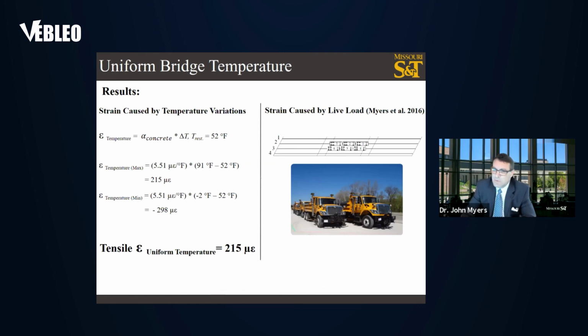Someone may ask, is thermal strain an important concern? To answer this question, we did a comparison between the strain induced from the temperature variation and the critical case of live load test. We found that the strain caused by uniform temperature is approximately 2.3 times the strain caused by an H20 dump truck on the bridge. So you can see that the strain caused is significantly different for thermal effects, so they can be quite significant. So 215 due just to temperature changes, and 95 due to 6 H20 dump trucks on the structure.